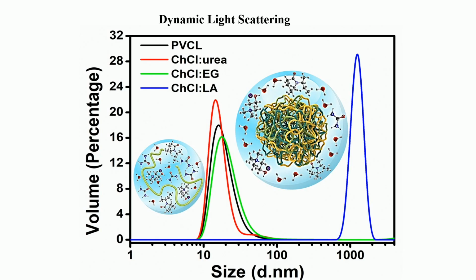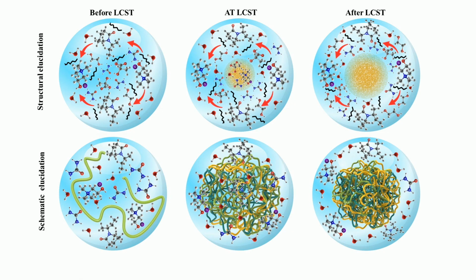The figure shows the dynamic light scattering measurements of PVCL in the presence of a higher concentration of deep eutectic solvent at 30 degrees Celsius. DLS results illustrate large size agglomerate formation in the presence of choline chloride lactic acid. This is the schematic illustration of deep eutectic solvent-induced alteration of the hydration layer in poly(N-vinylcaprolactam).